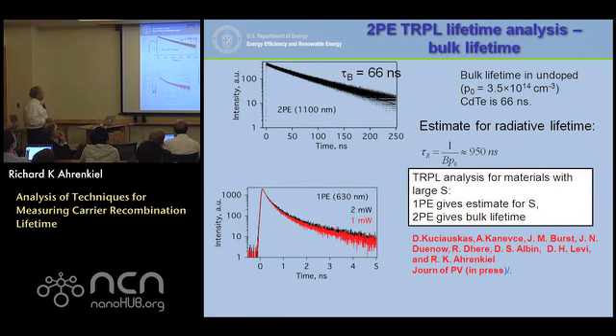Now this has been instituted by Darius at NREL, because we have a problem in a direct band gap material like cadmium telluride. We're working on cadmium telluride there, and he has some bulk cadmium telluride. And because you have the steep band-to-band transition, it's very hard to find a regime where you can get volume absorbed light. So he used the 2-photon absorption. He used a 2-photon absorption here, so he went out in the infrared, and the 2-photon absorption, which varies as the square of the electric field in the EM field, is quite weakly absorbed.